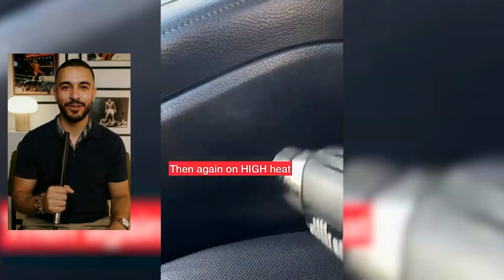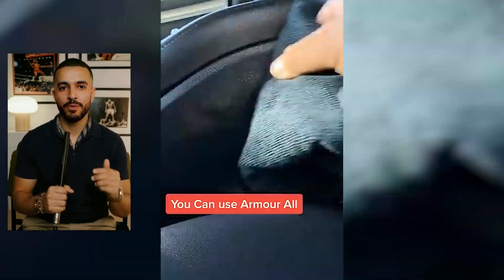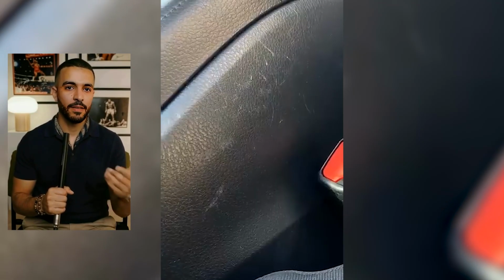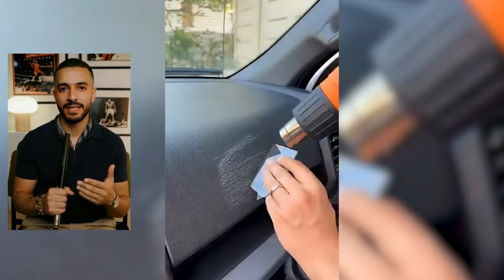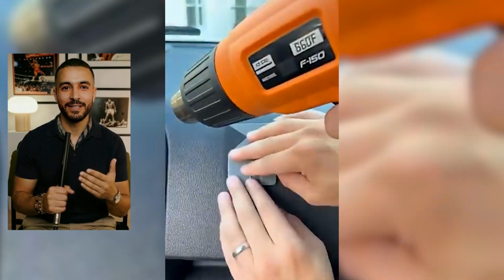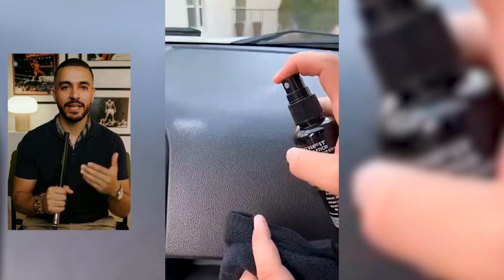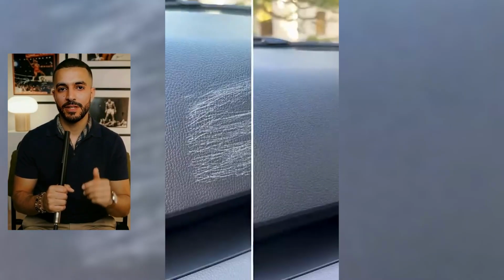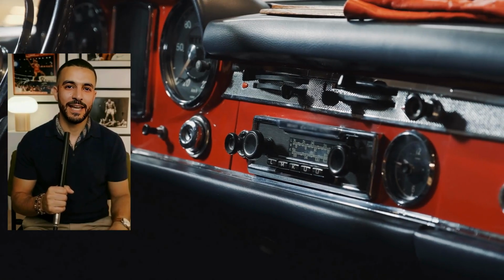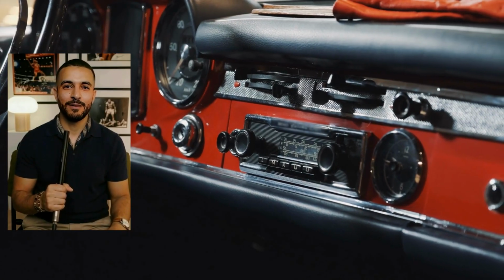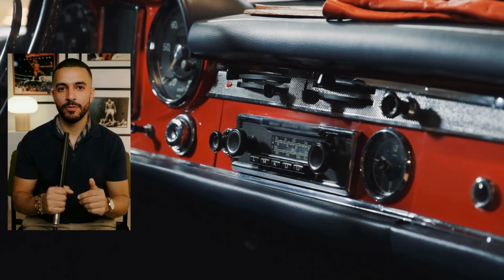You take a heat gun, wave it over faded plastic, and the gray turns black instantly. It feels like you've discovered a free, permanent fix. You haven't. What's actually happening? The heat melts the very top layer of oxidized plastic. It brings oils from slightly deeper in the material to the surface. It looks great. For about 3 to 6 months. Then the UV hits that newly exposed, completely unprotected surface, and it fades faster than before.